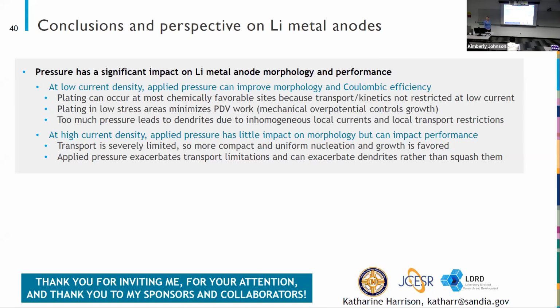In conclusion, pressure has a significant impact on lithium metal anode performance and morphology. I showed you that at low current density, when we apply pressure, we can improve morphology and coulombic efficiency. And the plating really will occur at the most favorable sites because there is not much in terms of transport and kinetic restrictions at low current. And that means that plating will be dictated by the mechanical overpotential instead of these other overpotentials. And we really have to do work to displace the interface to plate at high pressure regions. So we instead plate at low pressure regions, and the mechanical overpotential controls that growth process.